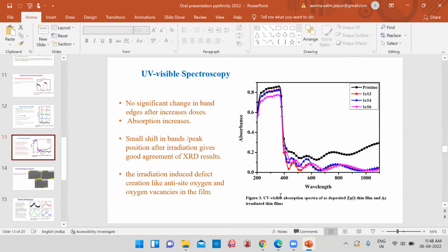These are the modes for pure ZnO. After irradiation, we just see the modification in the peaks, or if we dope with some metal, then we can see the modification in the peaks. It gives SPR peaks or something like that, so we can observe this. So these are the pure ZnO, all modes are visible, and we can see that the optical absorption increases after irradiation.